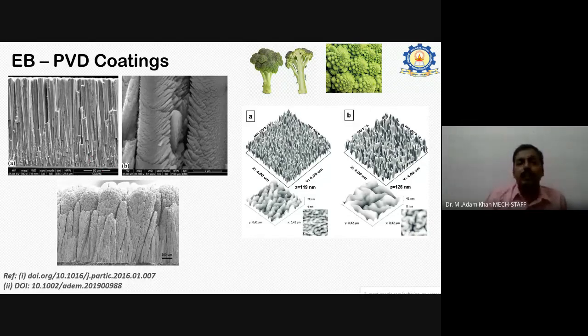So far you have seen the thermal spray method for thermal barrier coatings, but in early days people used to make thermal barrier coatings with the help of EBPVD, electron beam physical vapor deposition. The structure of this thermal barrier coating, developed through electron beam physical vapor deposition, looks just like a broccoli. At the top, you can see so many pores and voids, which have a higher surface tension to lead the fluids or gases floating over the top surface towards this. Not only at the top, you can see here how the gaps are created in this EBPVD. This is a fresh thermal barrier coating, so these are all needed.